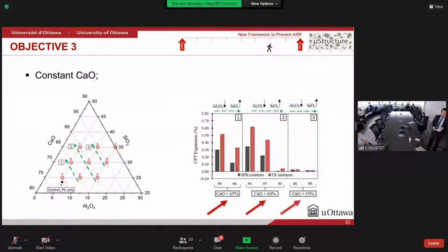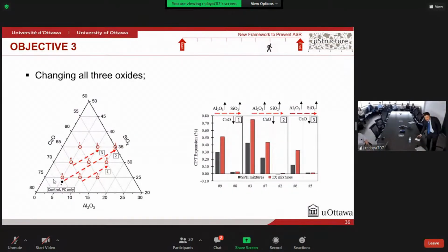And now, if we evaluate differently again, but now fixing the amount of calcium, we can clearly see that decreasing the amount of aluminum and increasing the amount of silica, there is a decrease in the final expansion of the concrete, indicating that indeed the amount of silica in the composition of the binder materials is more important to prevent ASR in concrete. And then just to emphasize the fact that decreasing the amount of calcium and increasing both aluminum and silica, we have a huge decrease in the final expansion of the concrete.